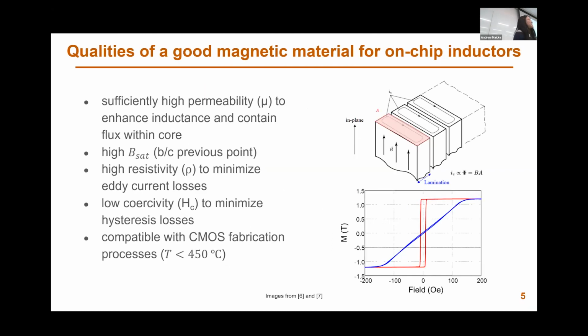And a good material for a core for an on-chip inductor should have high permeability, again, because the main function of the core of the inductor is to contain flux. It should have high saturation magnetization, because again, as Alyssa said, we don't really want to saturate a core. Also because we want particularly high permeability for the core to function. So once the core saturates, you don't have permeability anymore.